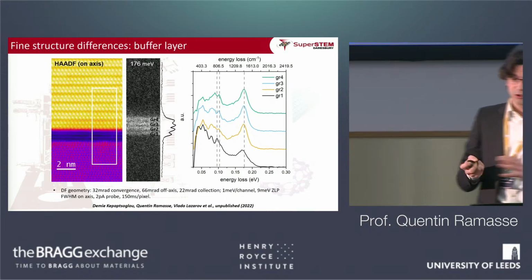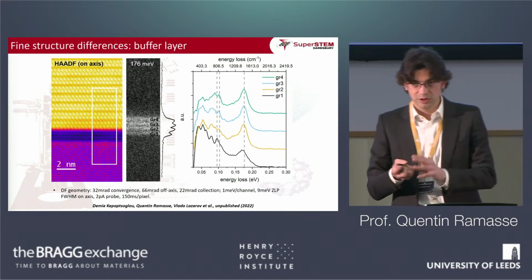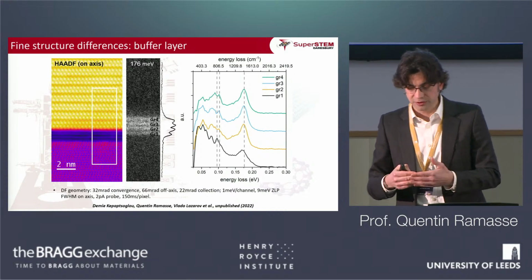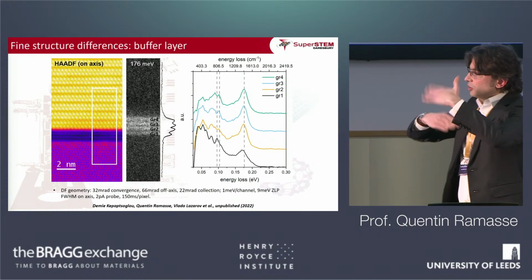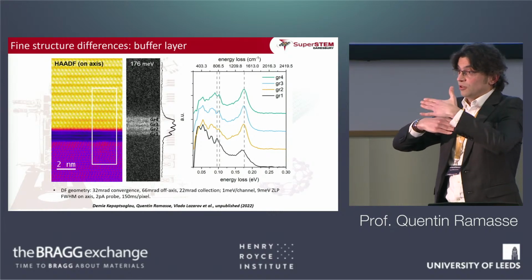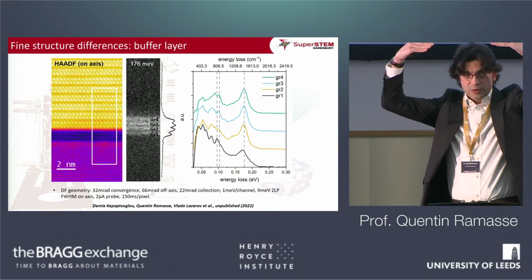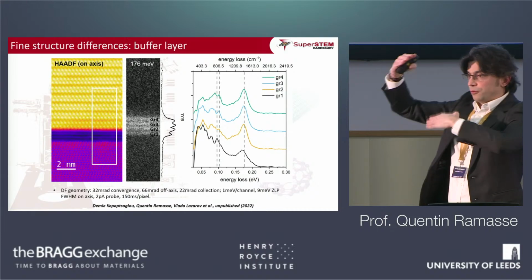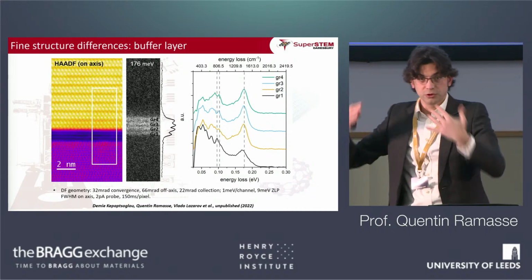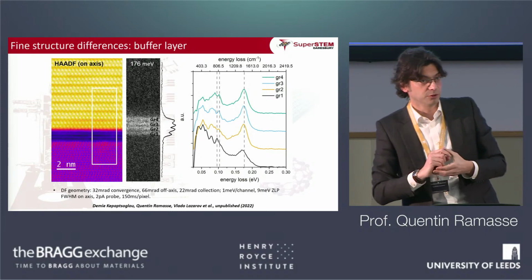And the reason for this, in a nutshell, just because I'm really running out of time, is that first layer somehow is still bonded. It sticks to the silicon carbide below. There's still some silicon to carbon bonds. The further carbon layers as you go above that, they're sort of free to breathe, they're free to move and free to vibrate exactly as you would expect from any material.